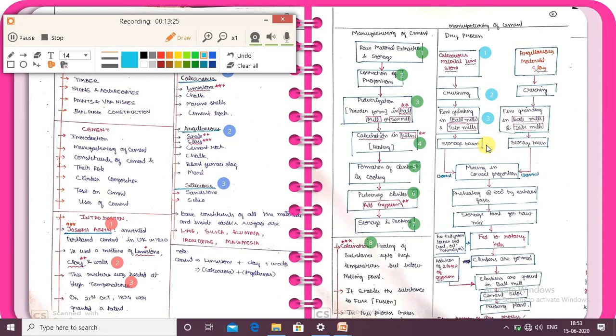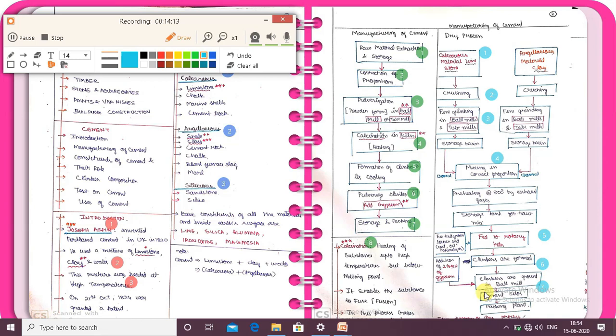Next step in the dry process: mixing in the correct proportion, then preheating at 80 degrees using exhaust gas. The material is then fed to the rotary kiln and heated to form clinkers. The clinkers are then ground in a ball mill, and 2 to 3% of gypsum is added. After grinding and adding gypsum, the material is stored in cement silos and sent to the packing plant.